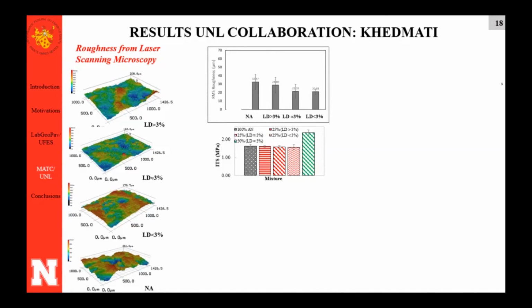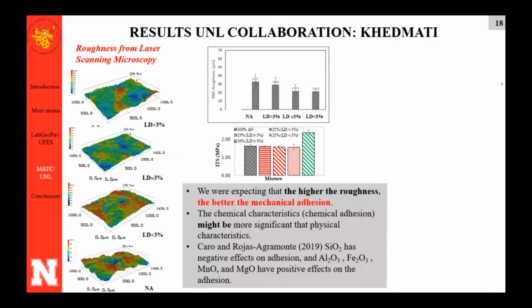But the roughness of the natural aggregate is higher. So why did that happen? I was expecting lower roughness for the natural aggregate, higher for the slag. Then I could say, oh, that's why slag has better performance, because higher roughness, better bonding between binder and aggregate. So maybe the chemical characteristics, not roughness, but the chemical characteristics that give the chemical adhesion, are more significant than the physical, the mechanical adhesion.